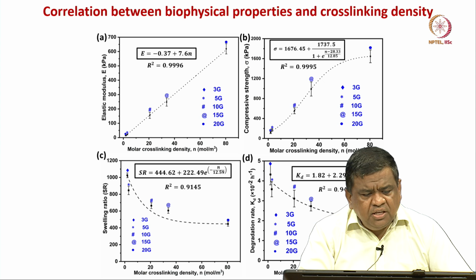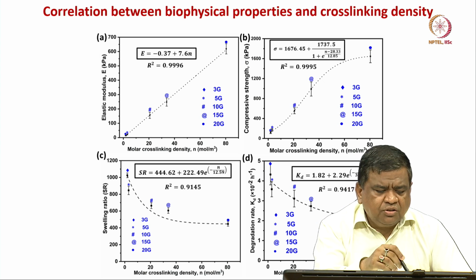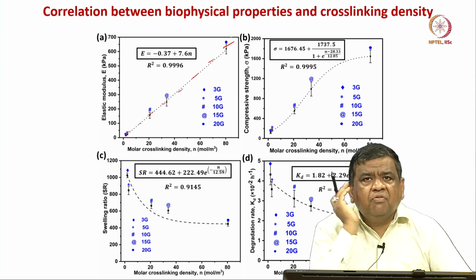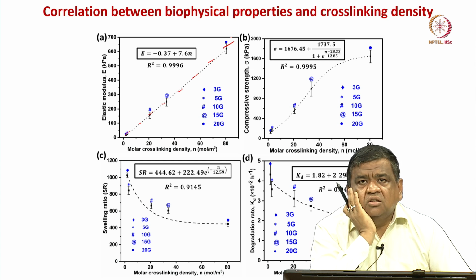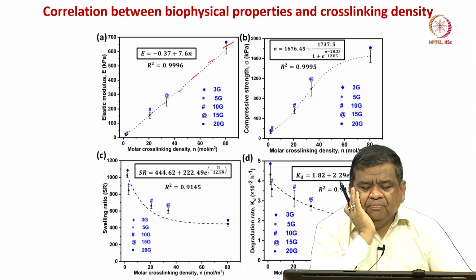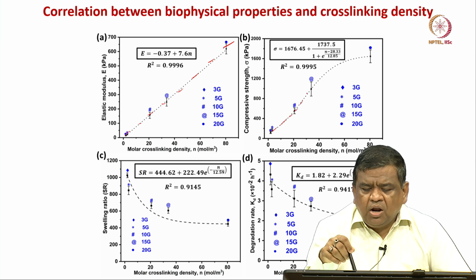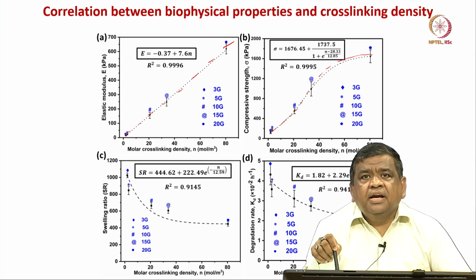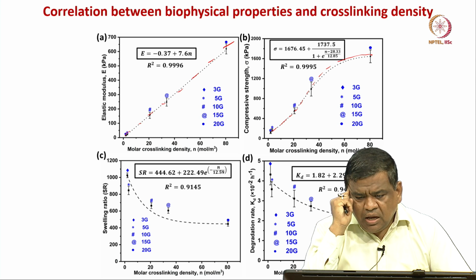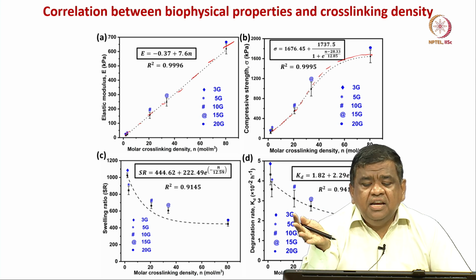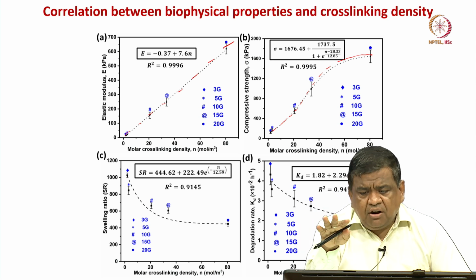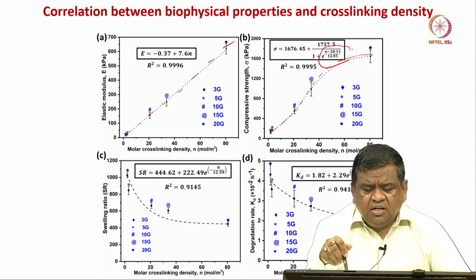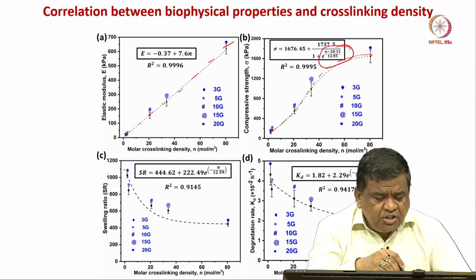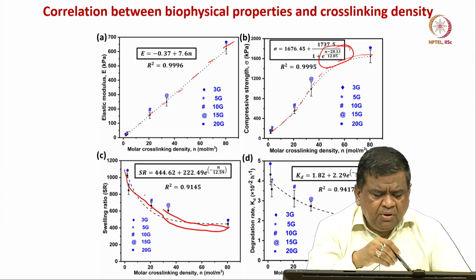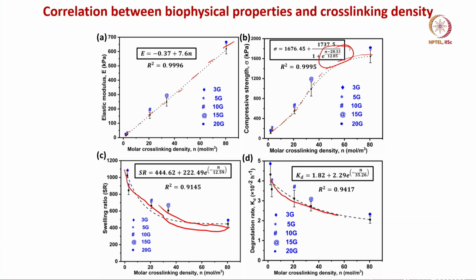And if you plot this elastic modulus as a function of the molar cross linking density, it shows a perfectly linear plot, right. So, y is equal to mx plus c type of plot. If you look at the compressive strength with the molar cross linking density, it is not linear, but kind of exponential type, because there is an exponential function. Swelling ratio shows an asymptotic behavior, like it goes down, and the same is the degradation rate.